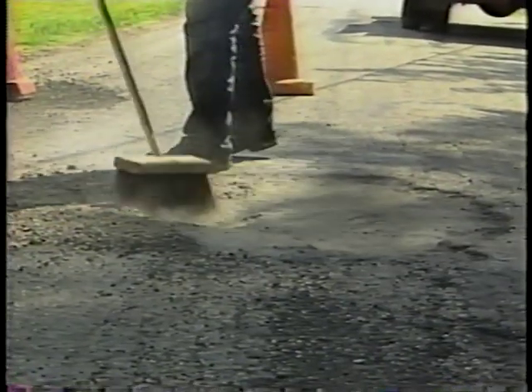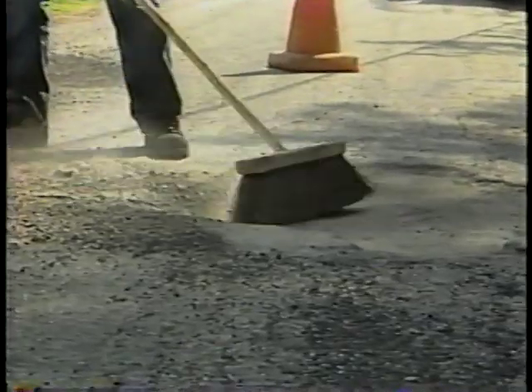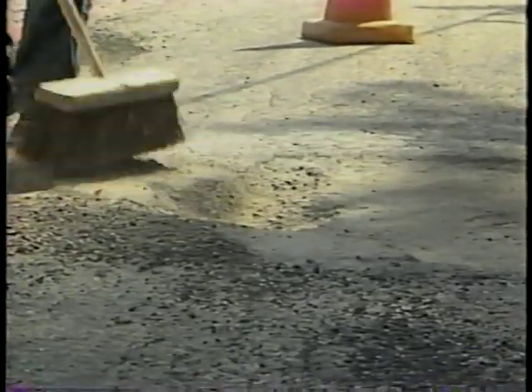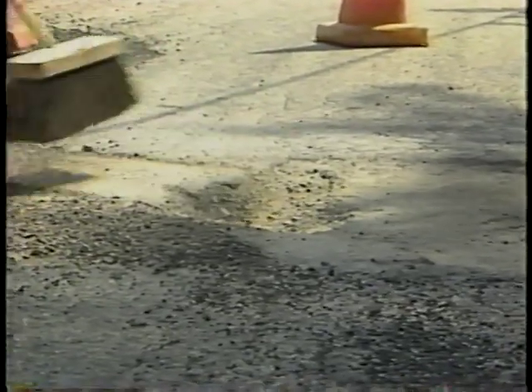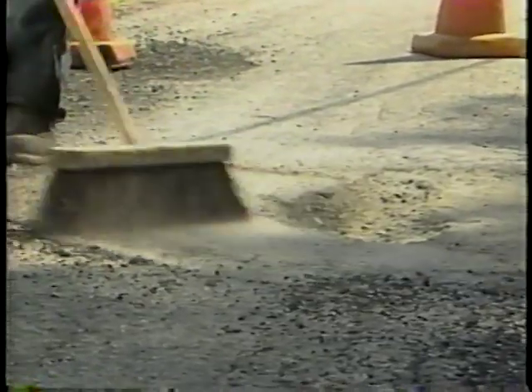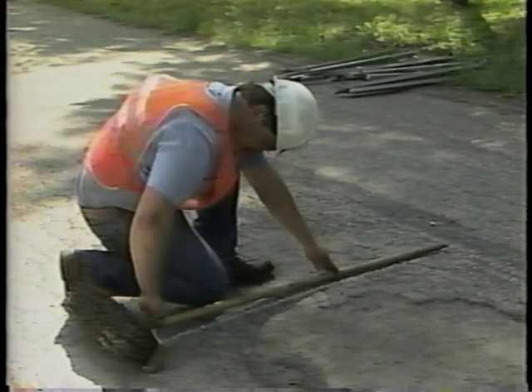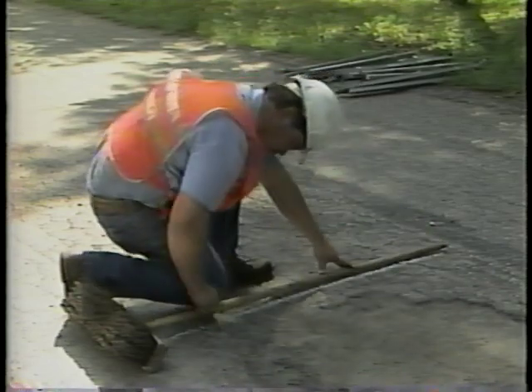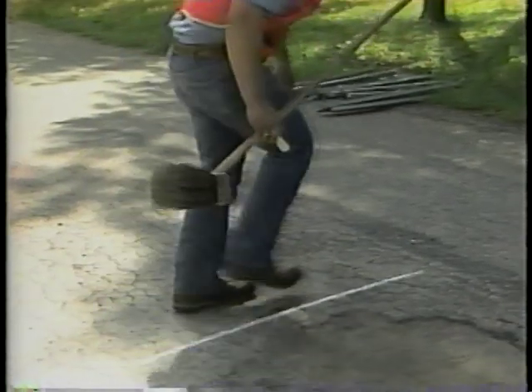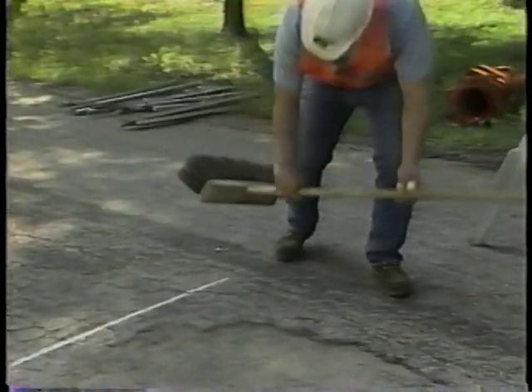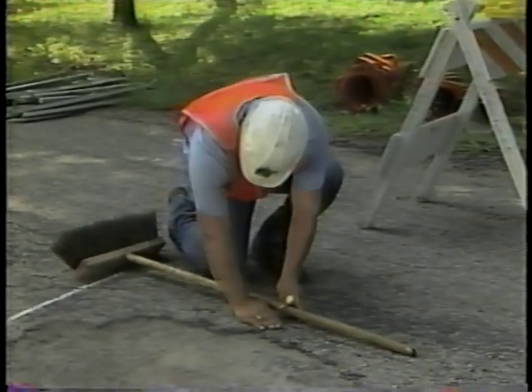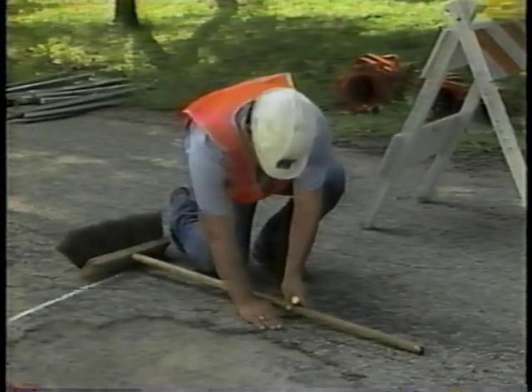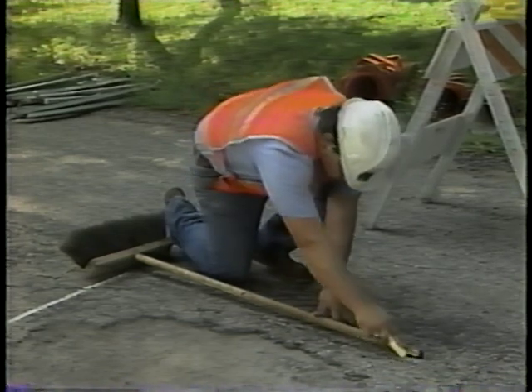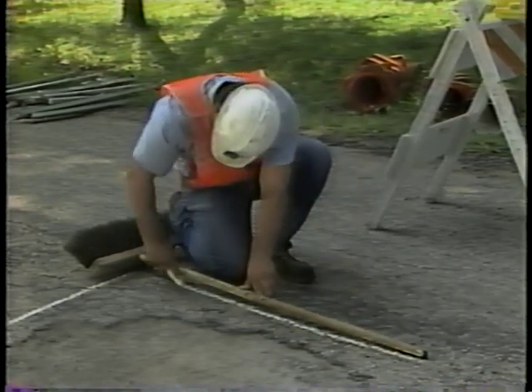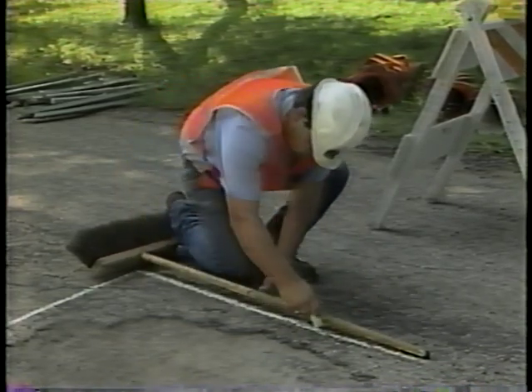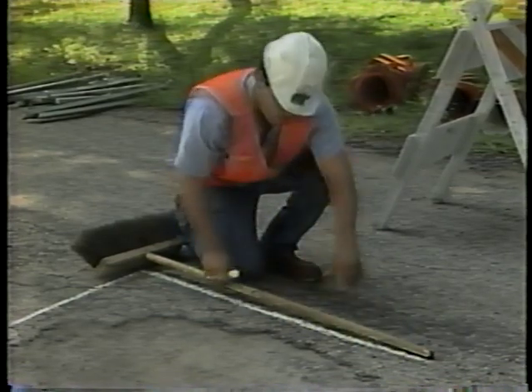Step 2. Mark the damaged area to be repaired. Before you mark this area, clean out the pothole so you can inspect it. Clearly mark the pavement outside the pothole. To avoid waste, the line should be no further from the hole than the width of your hand. The line should also be straight and located in good pavement. The corners should be as square as the shape of the hole will allow.